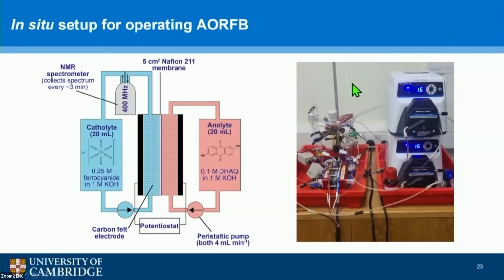So you can see here, these are 2 peristaltic pumps. And this is what pumps the electrolyte from the electrolyte reservoirs that are here. Sorry, it is a bit messy, it's not easiest to see. And then this pumps the electrolyte into the electrochemical cell, which is connected to a potentiostat. And this allows us to control the voltage of the battery and also the current, and then measure the changes in current as well. And then once it's come out of the cell, it goes straight into the NMR spectrometer.